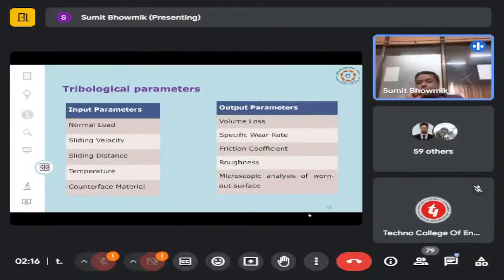So for input parameters, since we are investigating the wear behavior in the multi-tribometer machine with an ASTM standard, a cylindrical sample has been considered. There also some variation occurs. Whether the tribological behavior is measured at a specific normal load you have applied, or you are varying the load. Whether the velocity, the speed we are moving or rotating, is in one specific category or different sliding velocities have been considered.